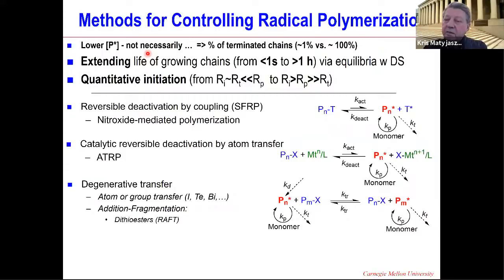So really the main distinction between conventional and controlled process is that in a conventional process, nearly all chains, essentially 100%, except this tiny fraction of actually growing species, are terminated. And in a controlled process, we have maybe 1% or 2% of terminated chains, and 98% are either in the form of active or dormant species. So the second important feature for synthetic purpose, which Craig so nicely articulated, is that you can extend the life of propagating chains from seconds to hours. And we do that by equilibration with various types of dormant species.